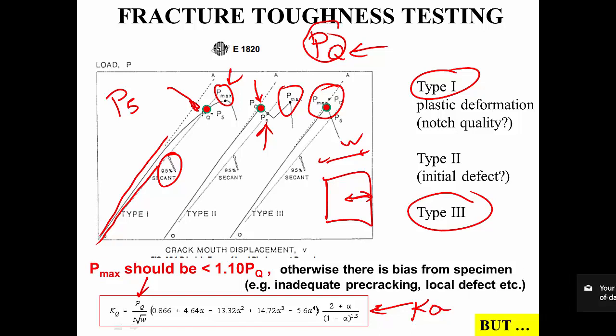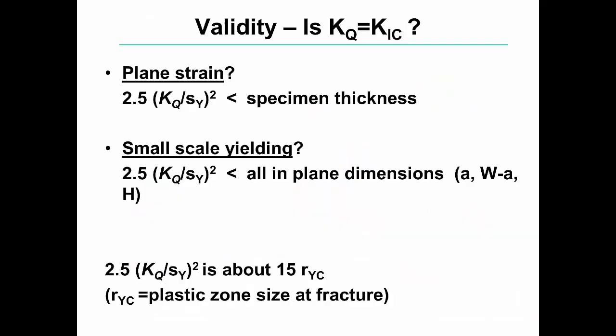It can be, but we need to test for it. So how do we test whether this value is appropriate or not? There are two conditions that need to be satisfied. If these two conditions are satisfied, then we say yes, the value that we calculated is indeed the plane strain fracture toughness of the material. So the first condition is to have plane strain conditions satisfied.